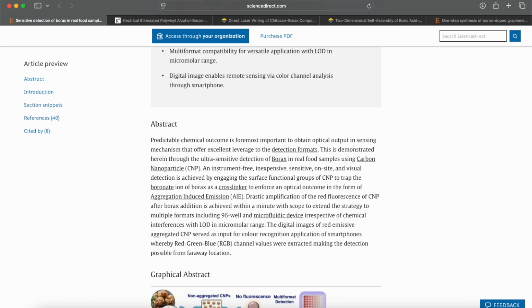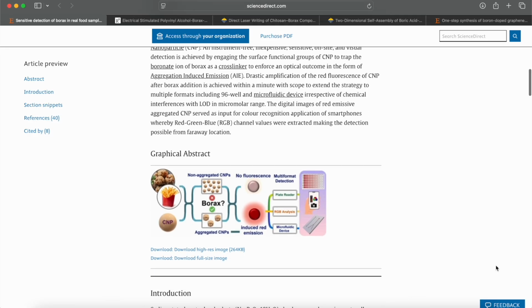Drastic amplification of the red fluorescence of carbon nanoparticle after borax addition is achieved within 1 minute, with scope to extend the strategy to multiple formats, including 96 well and microfluidic device, irrespective of chemical interferences, with LOD in micromolar range. The digital images of red emissive aggregated carbon nanoparticle served as input for color recognition application of smartphones, whereby red, green, blue RGB channel values were extracted, making the detection possible from faraway location. And here we have a lovely image.